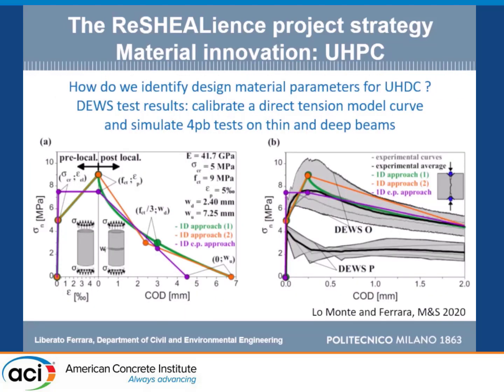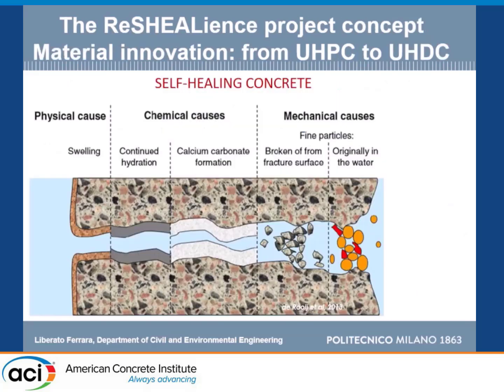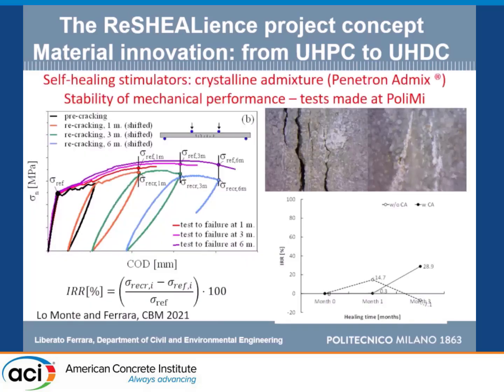And the signature feature of this material is that it develops a strain hardening response under tension, which makes it different from conventional concrete. We identified, obviously, the mechanical properties according to different tests, but we also wanted to promote a signature durability feature, its capacity to self-fill the cracks, mainly due to continued hydration and calcium carbonate. And you can see here some images.